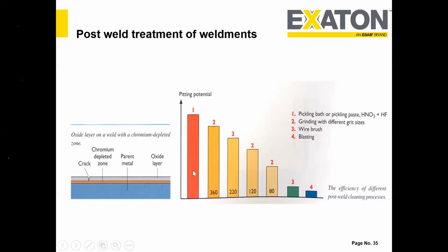So pickling and passivation is the most important thing, which gives the maximum potential. We do the acid cleaning, then we neutralize the acid. Naturally, the chromium present on the weld metal or base material gets in contact with the oxygen in the atmosphere and forms a stable passive layer of chromium oxide. Now number 4 is brushing. Brushing could also be done, but it is not as good. So brushing, then wire brush, then grinding, and then pickling and passivation. So we recommend, if you want to get the highest pitting potential, you should go for acid pickling and passivation.